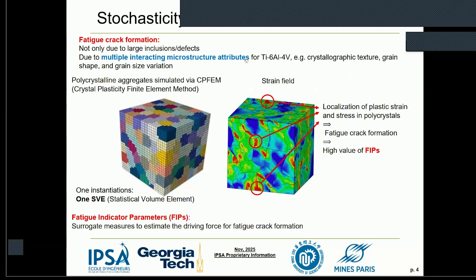And for some recent works, we also know that for some other alloys, such as titanium, the fatigue crack initiation is completely different. This is not only due to large inclusions or defects. The fatigue initiation is also induced by multiple interacting microstructure attributes, such as textures, grain shapes, grain size variations, and so on. So this is an example.